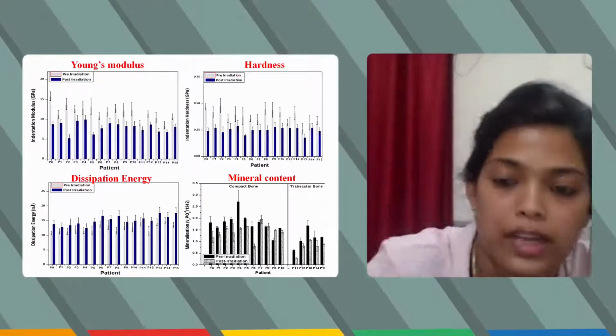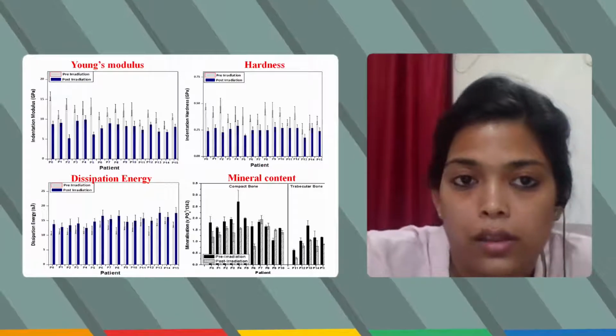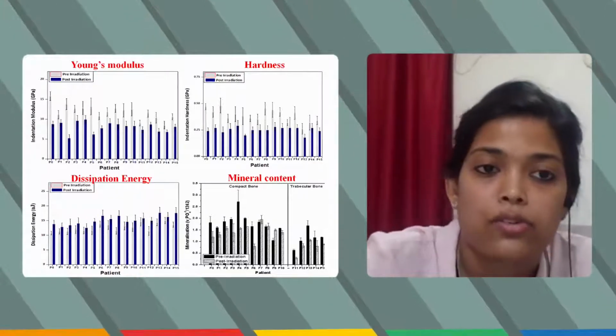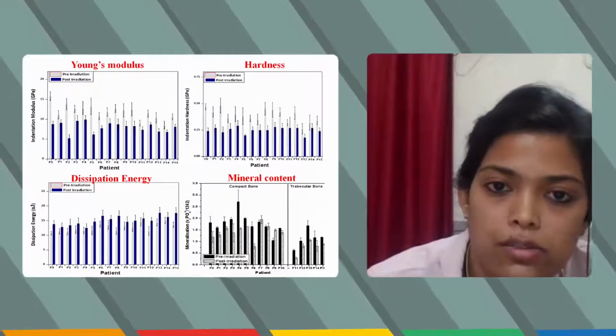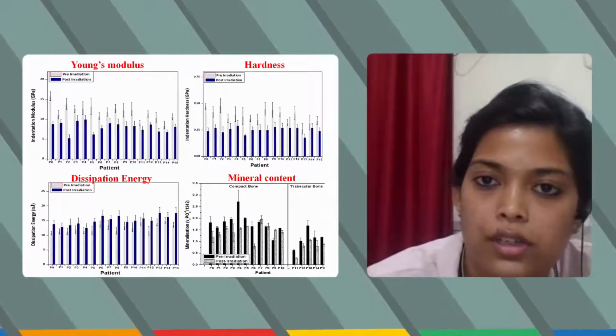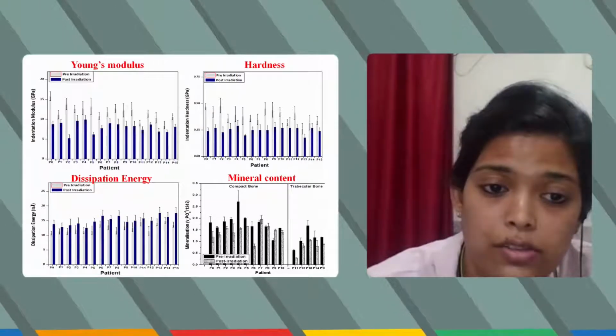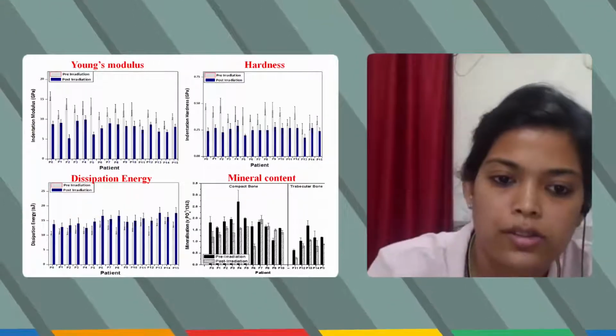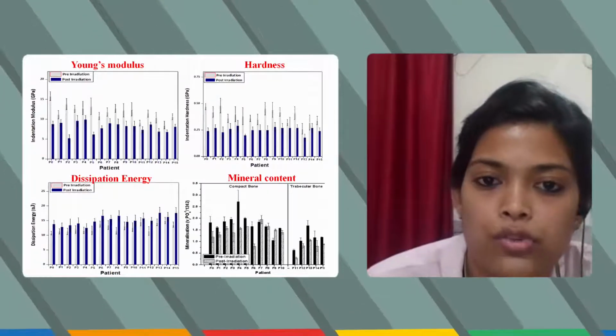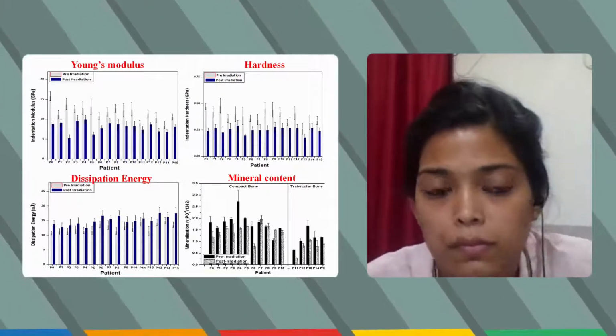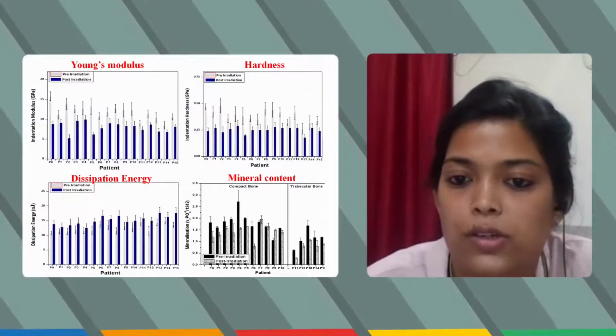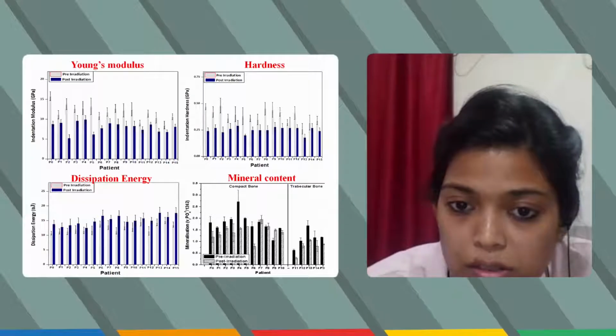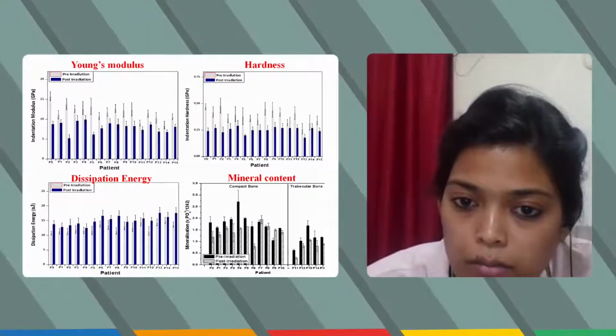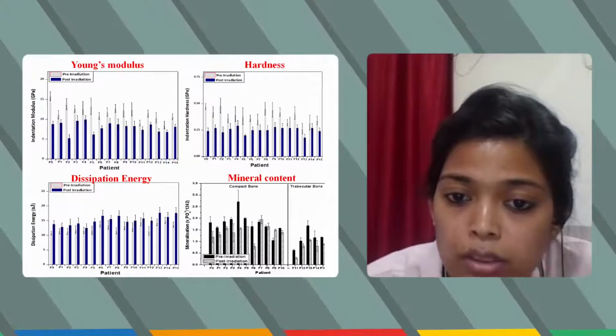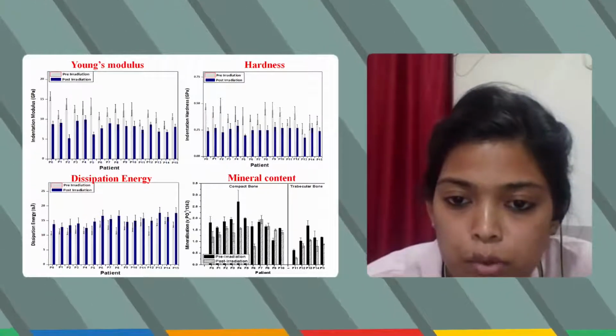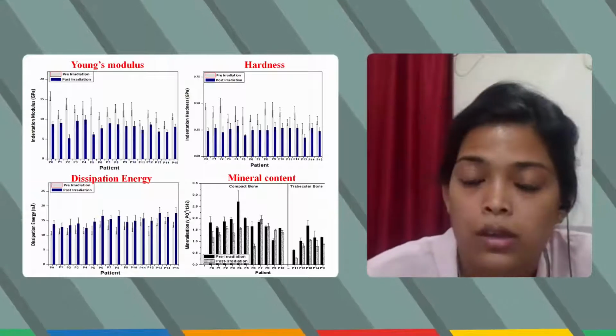So how the bone reacts, I'm coming early to the results. By nano indentation, we acquired results that Young's modulus of the bone post irradiation is severely decreased, while hardness is also severely decreased. But the dissipation energy increased in all the samples throughout all the patients, from patient 0, which is the control, to patient 15. And mineral content is also decreasing. For patient 0, you can see there is a 1.8 in the pre-irradiation sample, while it becomes a ratio of 1.2 in the post-irradiation sample. There is a heavy decrease in mineral content.